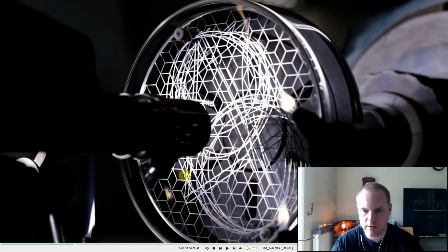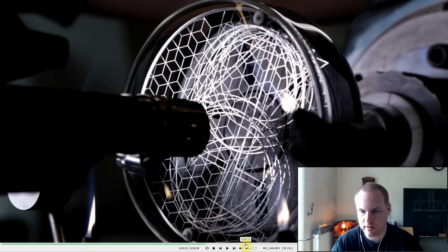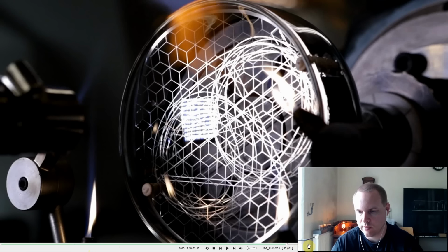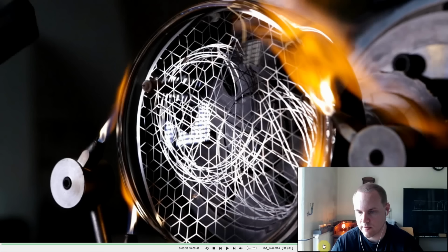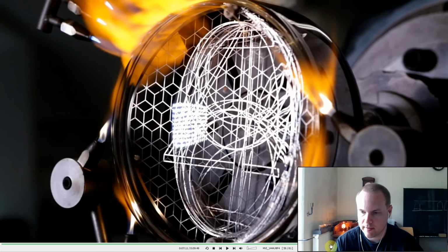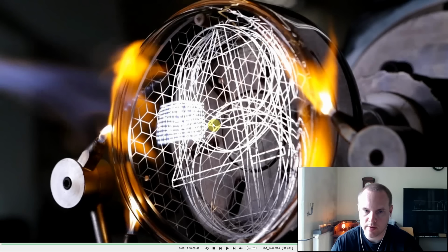So this is the second tube with the holes in the glass. I will skip the purging phase and I will go directly to the end of the sealing process. Here we have the camera shutter speed set to 1/1000 of a second, so we can still see the digits sharply. And so here is the end, and as you can see, at the end of the sealing, when the edge is completely done, the digits are still silver. I don't see any sign of oxidation on them.